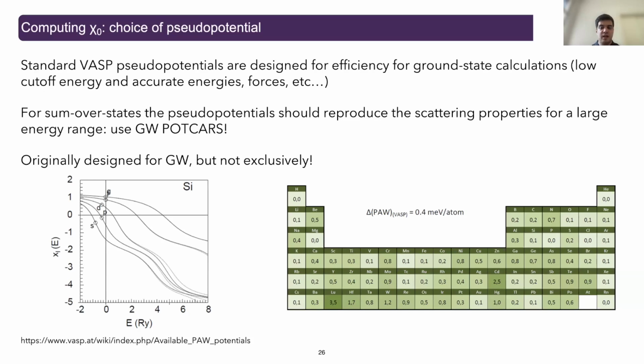As a final remark, I would like to emphasize that some elements have different pseudopotentials, and the difference between the files is the number of electrons that is considered as valence electrons, and those which are considered as belonging to the core. So you might need different potentials depending on the material and experiment that you're trying to describe. For instance, if you're trying to describe Kerr measurements where magnetization is important, you should probably consider using pseudopotentials that include the electrons, so that the magnetization is computed accurately.